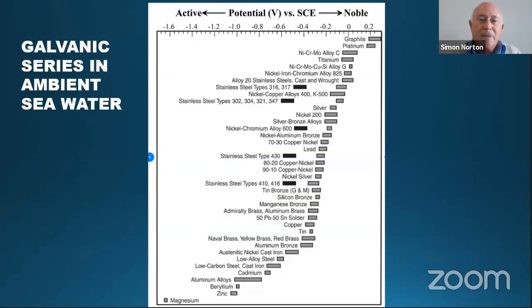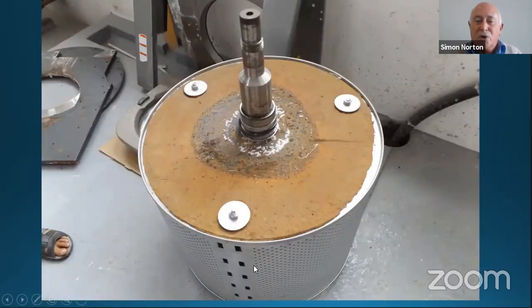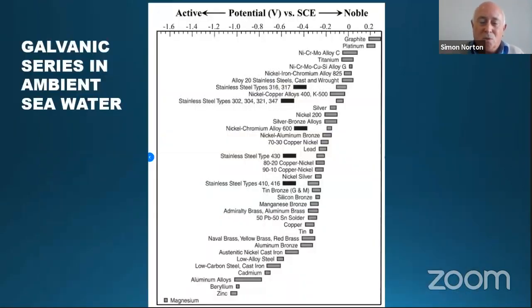We don't think it did, but there is a possibility that it might have contributed to it. Just out of interest, there is the galvanic series. And if you look at the top here, you'll see that towards the noble end, stainless steel 316 and stainless steel 430 sit over here. And right down the bottom here is low carbon steel. So if you go back to this photograph, you've got two materials far apart, immersed in an electrolyte and with a contact position. And then the ratio of areas, well, you've got a large stainless steel drum and a much smaller anode made up of the mild steel. However, we think this is not what actually happened.